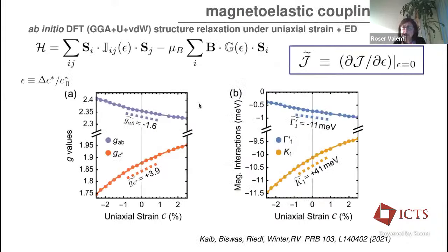And then what you can do is analyze the exchange interactions as a function of strain, as well as the g factor. Let me go to this here on the right. One sees that by applying this uniaxial strain, where you basically expand the honeycomb lattice, the Kitaev interaction indeed increases, and increases rather strongly, and you are getting rid of these non-Kitaev interactions. So this is in fact a very promising type of experiment. And then you can extract out of that, by doing the derivatives, the magnetoelastic couplings.